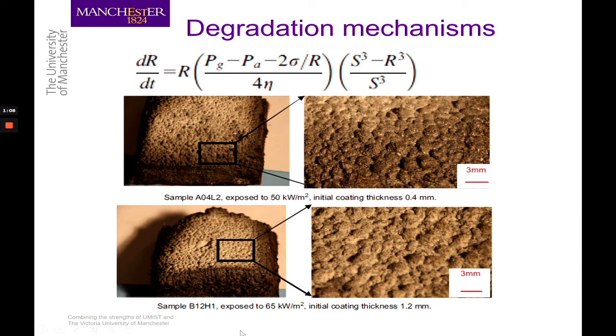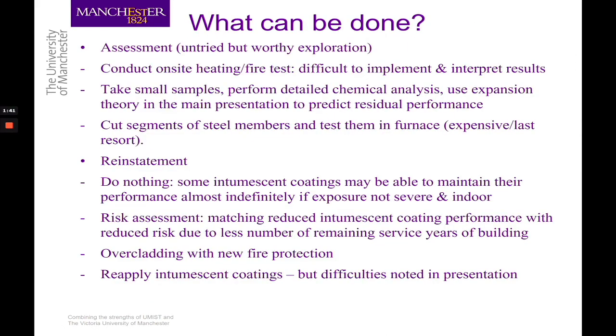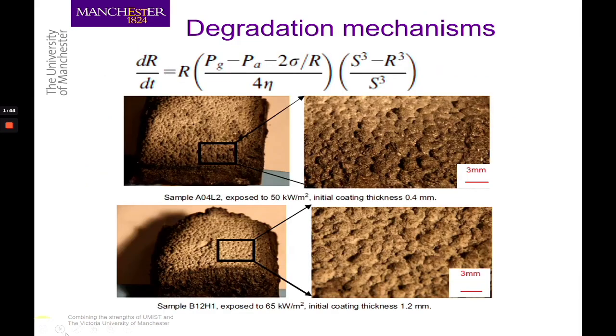At temperatures of around 150 degrees, the acid source melts and reacts with the carbon-rich component, which will eventually become the char. This then becomes a viscous liquid. In the meantime, the blowing agent decomposes and produces gases. These gases will then expand the intumescent coating liquid, which eventually, as I said, becomes char. All these reactions have to happen at the right time, at the right amount, at the right rate to make sure that the intumescent coating is working.